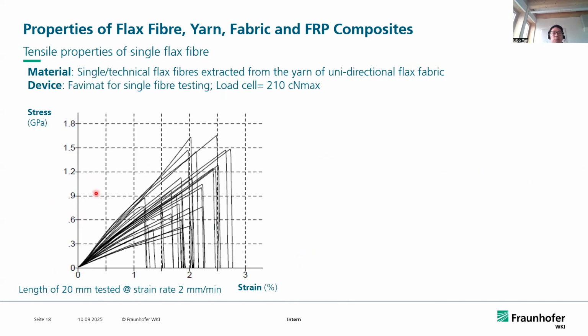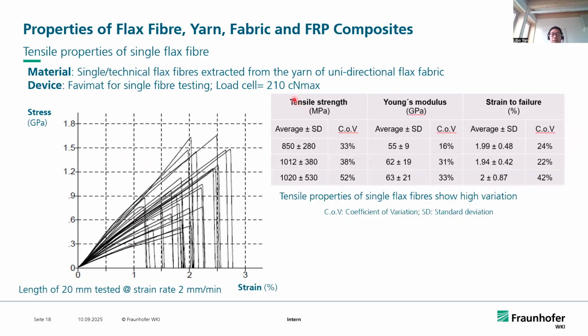Afterwards, let's move on to the tensile properties of the single flax fibers. The flax fibers are extracted from a yarn of unidirectional flax fabrics. In these tensile stress strain curves, we can see the significant scatter of the results. On average, the tensile strength of the single flax fiber is around 850 to 1000 megapascal. The modulus is about 55 to 63 gigapascal, and the failure strain is about 2%. So the tensile strength and the tensile modulus are respectable.